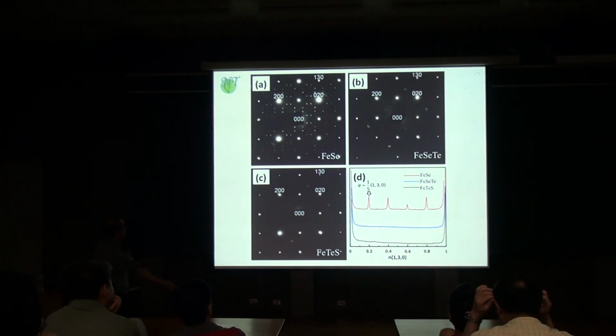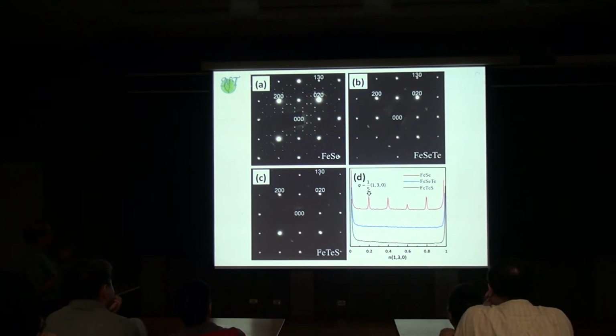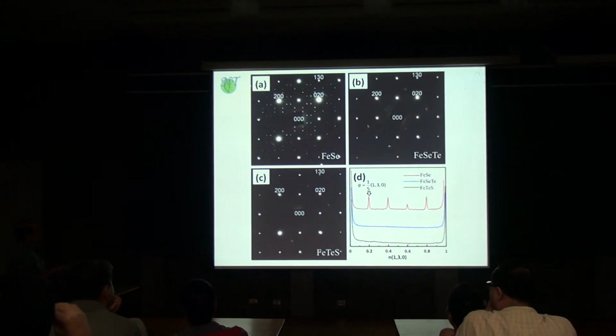Maw-Kuen, I think, is in the audience, and was good enough to immediately look at the TEM, and this is the diffraction. Beautifully, in addition to those tetragonal spots, you see those rings. By simple analysis, this is the superstructure with square root 5 by square root 5 order, exactly the same as the 245 I just mentioned. So we don't need potassium here.